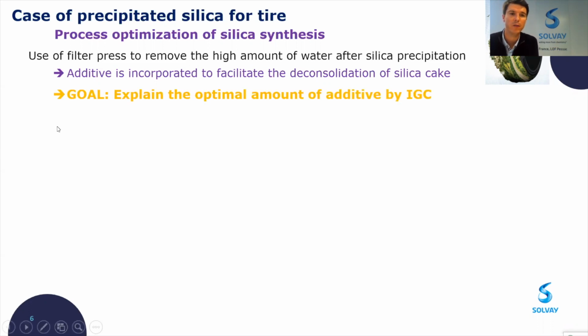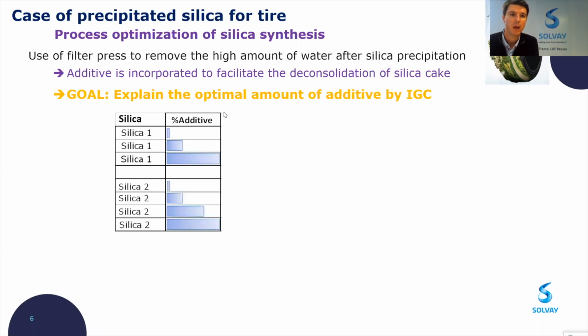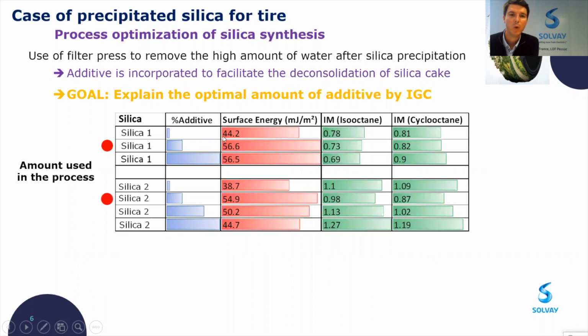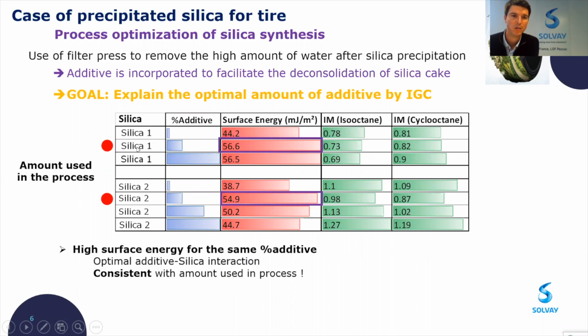And here the goal is to explain the optimal amount of additive by IGC. For that, we have compared two types of silica, and we have modified the quantity of additive at the surface. And here, with the red points, you can see the amount used in the process. And when we determine the surface energy and morphology index, as you can see here, we have a maximum value corresponding to the amount used in the process. So it's very consistent with the application.